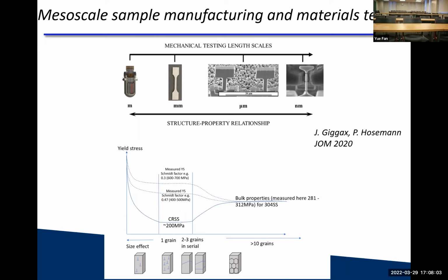But if you have an irradiated material, in some other work not shown here necessarily, you actually see that it stays high. In that instance, the strength determining feature is not the grain size or the orientation, it's the radiation effects. We just published a work with our colleagues in the UK, Chris Hardy, where we looked at chromium precipitates in copper, and you can very nicely tailor the precipitate density with that system. If you tailor it just right, you actually stay pretty much constant all the way. Because if your strength determining feature is very small, then the dislocation density plays no role, because that's not the strength determining mechanism.